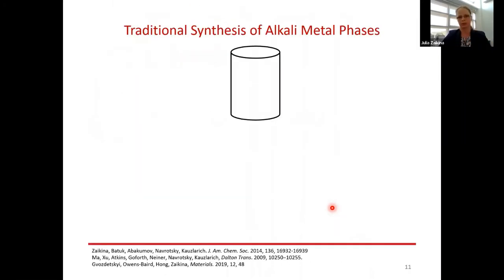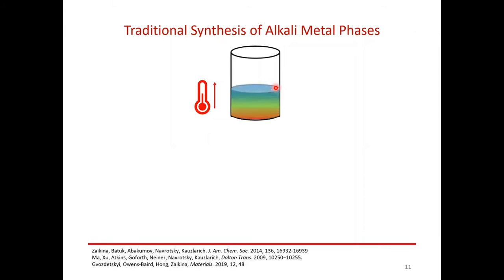that brings additional challenge. Because in the traditional solid state synthesis, we would mix elements and then add the alkali metal. But because alkali metals, they are soft, ductile metals, they cannot be really mixed with the rest of the powdery precursors. So we would need to add them in pieces, and then we really need to go to high temperature so the alkali metal melts, which allows it to mix with the rest of the components in our reaction mixture. But even at high temperature, the melt would be inhomogeneous in composition.